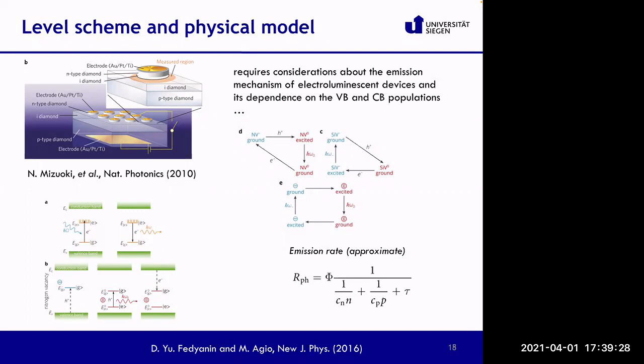Anyhow, we made a theory for this which was published in 2016, and what is interesting for us at the end is the emission rate. The emission rate, so how many photons you can get out of this color center by electrical pumping, can be approximated by this equation, where you have phi, which is the quantum yield of the color center. So basically, the probability that you get a photon when you go from the excited to the ground state.